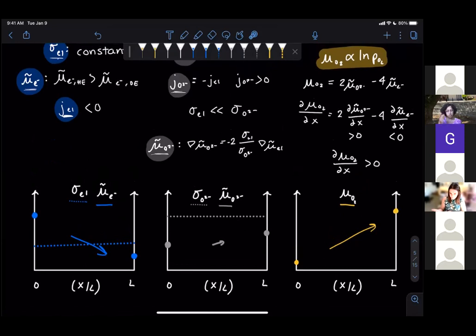And so as a teaser, it's important that we make sure that the chemical potential of oxygen, or whatever neutral species you're considering, it could be lithium, for example, solid lithium, is not going to be favorable for oxygen to exist in the solid electrolyte. You want it to stay ionic and you want it to stay as electrons, and you don't want the prevailing species to be an oxygen gas bubble or a solid lithium.